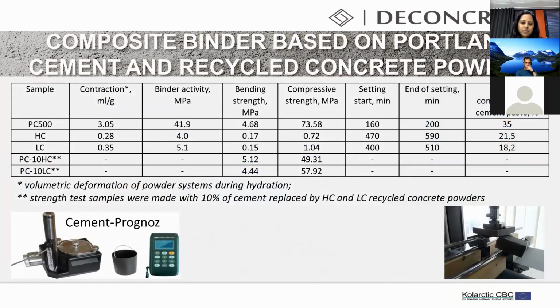And next, we make several different composite binders based on Portland cement and recycled concrete powders. The first row is Portland cement only, 100%. It has contraction of about 3.05 milliliters per gram. Contraction is volumetric deformation of a powder system during hydration. We use this value to predict binder activity, how much strength it will have at 28 days of curing.